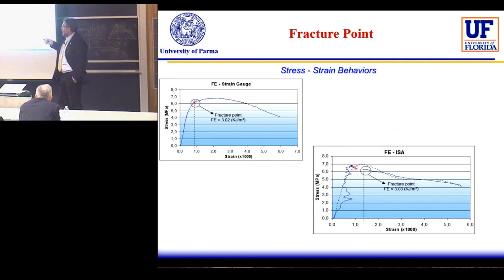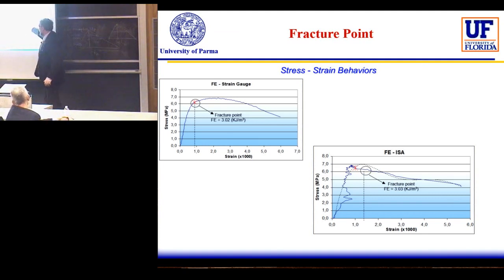The strain analysis was made using the strain gauge in the back of the specimen and the DIC in the front. It was necessary at that time to have two different measurement techniques. In particular, this was used as a proof that the DIC method was giving us the right strain field, because we were at the very beginning. I'm talking about, I think, 2005. At that time the use of DIC was not common, so a lot of people were concerned about the real capability of that method to give us the strain field. As you can see, the strain curve from the gauge is of course clearer and better defined, but at the end of the story, considering some noise due to the vibration during the test, we are more or less in agreement with what's happening in the front and in the back of the specimen.